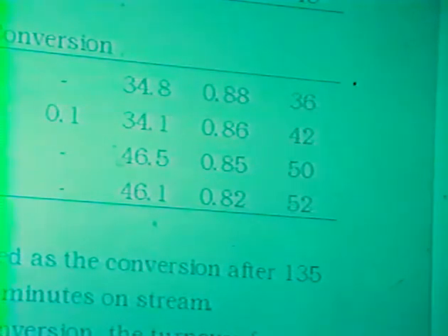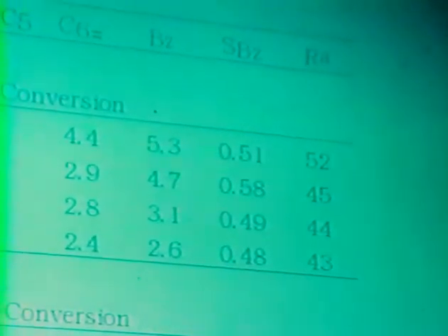That only occurs when we look at high conversion. Actually, if we look at low conversions, it's the inverse. Pure platinum has better stability than the platinum and nickel. Why should they be different? Well, that's probably the result of the intermediate that is formed. That is, at the low conversions, you get a fairly large amount of just simple dehydrogenation to C6 olefins. And when you have a lot of the olefin intermediate, then you get a lot of self-coking. On the other hand, at these high conversions, there's almost no olefins, and then the nickel has a positive effect.